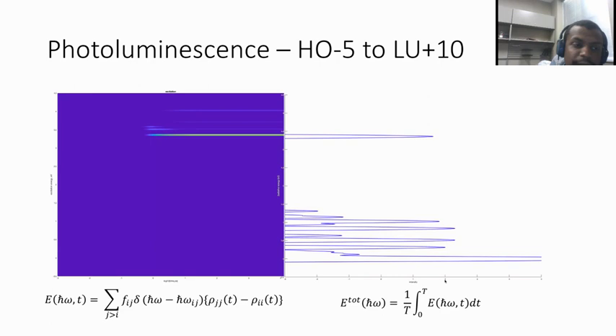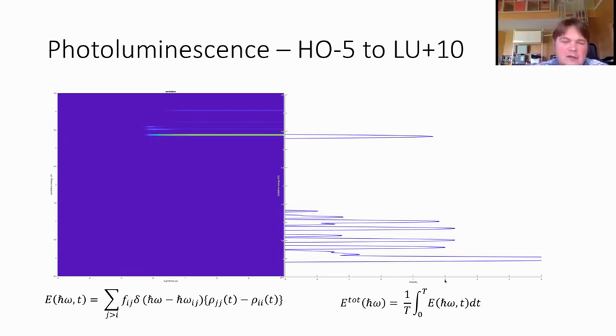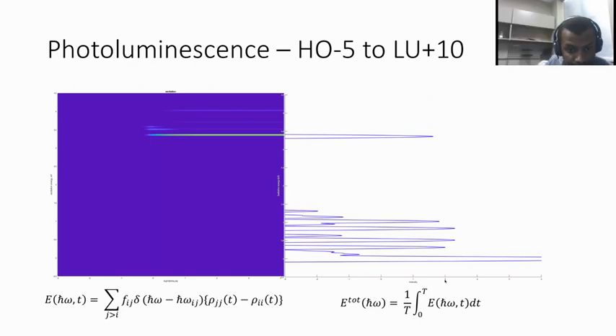Okay, I understand. And that means that there will probably be more recombination the more we excite at higher energy, then. Because anyway, it will happen on the order of picoseconds. When you excite at higher energy, you are correct. Strictly, there will be more channels for radiative recombination. But there is no time to launch them, because instead of recombining radiatively, it will quickly relax to the HOMO-LUMO. The channel of relaxation is quicker, more intense, and more preferred than radiative emission. Okay. Yes, that makes sense. Thank you.